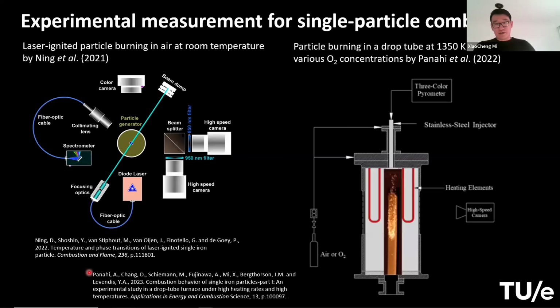And an independent experimental study was done by Panahi in the US. They use this drop tube reactor. The particles are injected from the top going downward. The gas is already hot enough to ignite the particle due to this heating element. And the pyrometry looks down from the top to monitor the gas and the particle temperature history.